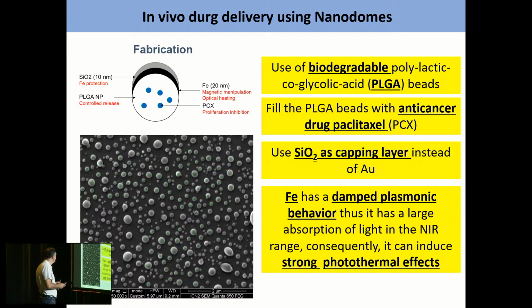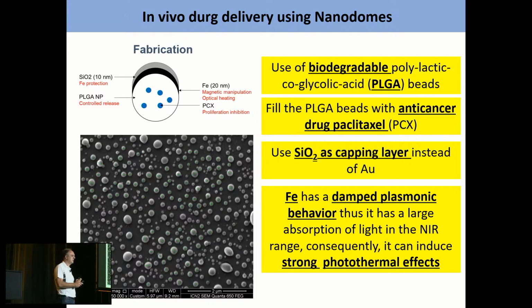This is because we found out that iron actually is plasmonic. It's not as good a plasmonic material as gold, and it has what is called a damped plasmonic behavior, but it still can absorb light and generate heat with the iron alone, without the need to put in gold, which is expensive, and you don't want to waste these kinds of materials. And actually, as I'm going to show you, this approach, using iron alone, also has a strong photothermal effect.